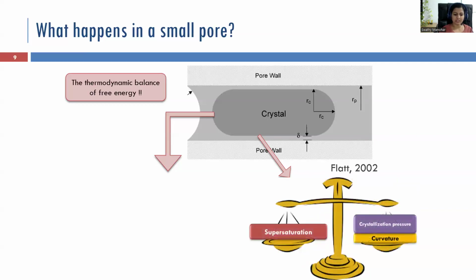Now you have crystallization pressure on the pore walls. This will generate hoop stresses around the pore walls. If the tensile strength of your material is higher than this hoop stress generated, you will not face damage. But if the hoop stresses are higher, you will have cracks and damages initiated there. That is how crystallization pressure causes damages in your system if you have smaller pores.